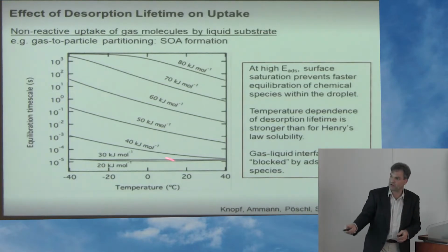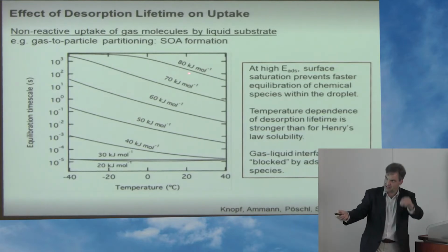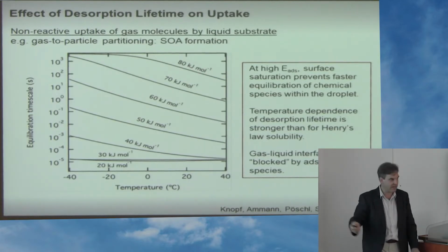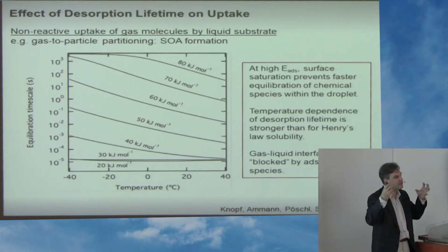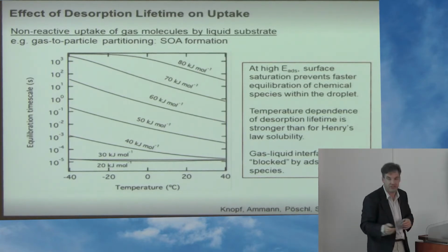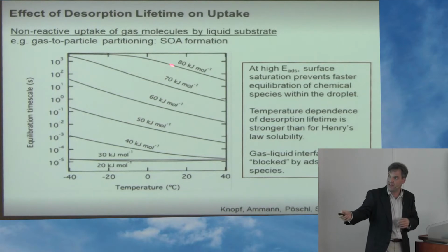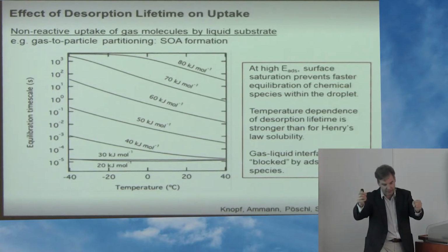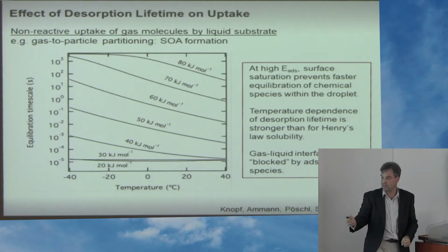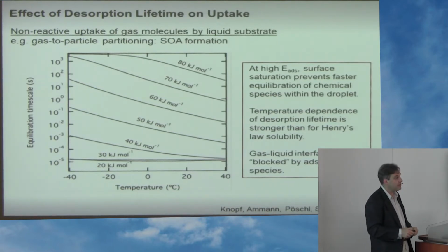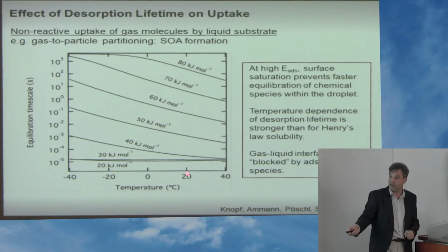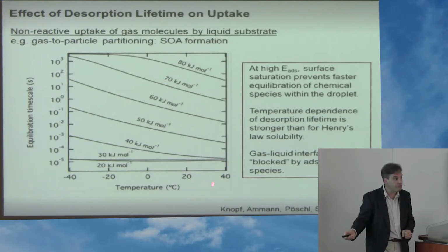And here we also have strong temperature effects when the condensing organics have a high adsorption energy - and these are huge molecules, they usually have high adsorption energies. What you see is this equilibrium timescale - that is, when is a particle in equilibrium with the gas phase? We have big differences between room temperature and lower temperatures, and again, we do all our chamber studies at room temperature.